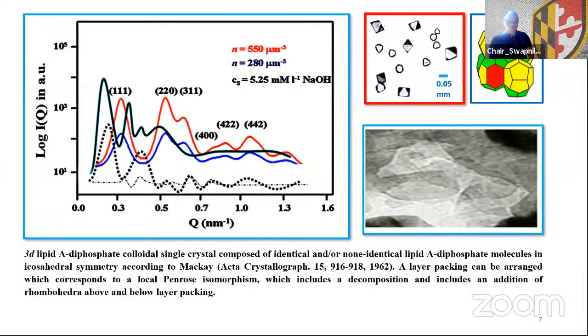Figure 7 shows colloidal single crystal composed of identical or non-identical lipid A diphosphate molecules or approximates in icosahedral symmetry and arranged according to Mackay, published in Acta Crystallographica 1962. A layer packing can be arranged which corresponds to a local Penrose isomorphism, which includes a decomposition and an addition of rhombohedral above and below layer packing. On the encircled red one box, it shows a single crystal of 0.05 millimeter of lipid A diphosphate, whereas the other one is just a packing of icosahedral faces according to Penrose.